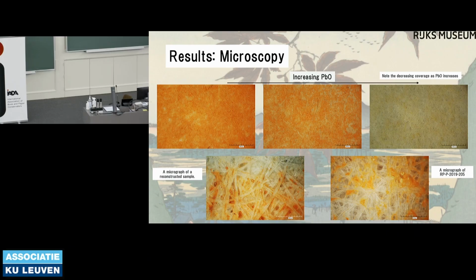When examining the reconstructed samples under magnification, several things became immediately apparent. The ratio of red lead to lead monoxide seemed particularly significant to how the samples appeared, and the grind of the pigment affected the appearance of the samples, but not nearly as much. It can generally be said that red lead created a uniform layer across the print, which entirely covered the porous surface, but as more lead monoxide was added, the layer became thinner and more uneven. When comparing the Rijksmuseum's prints to my reconstructed prints under the microscope, it was found that the non-discolored areas of the prints most resembled reconstructed prints printed with the pigment mixture rather than the pure red lead, and both samples were found to have incomplete coverage with paper fibers still visible and had pigment particles of varying sizes. So this is an example of one of my reconstructed samples, and this is a micrograph of one of the Rijksmuseum prints, and I find them to be quite similar.